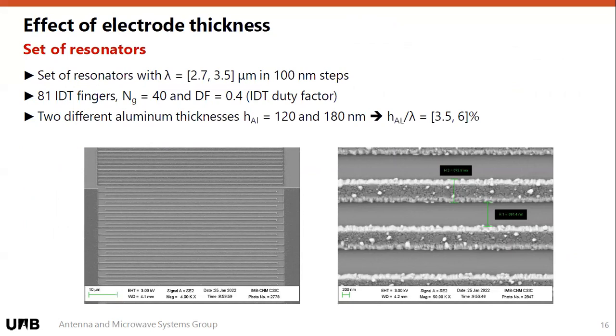So what we did initially is try and experiment with the thickness of the electrodes. And we manufactured a set of resonators. We swept around lambda in 100 nanometer steps to get a range of frequencies around the working frequency. And we went for 81 IDT fingers. This is a normal measure to have a normal sized resonator providing around 0.5 picofarads of capacitance, which should be enough. Number of grating fingers 40 and duty factor 0.4.